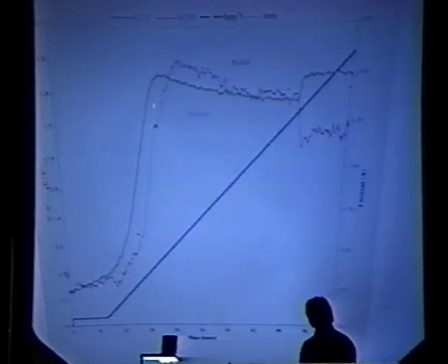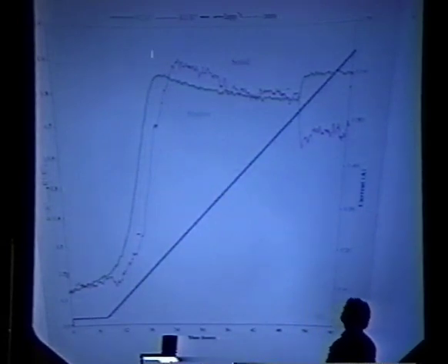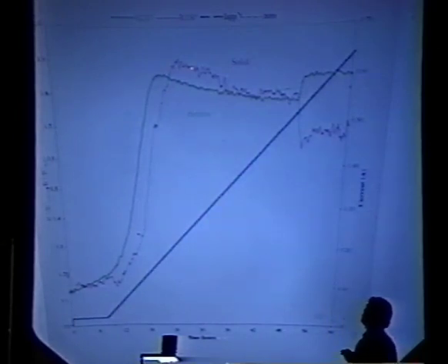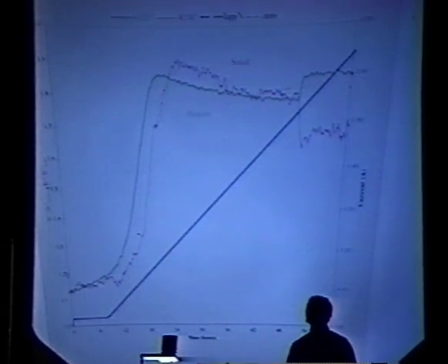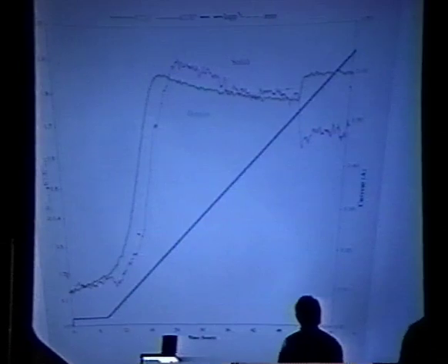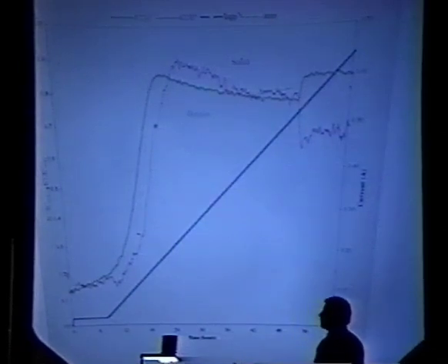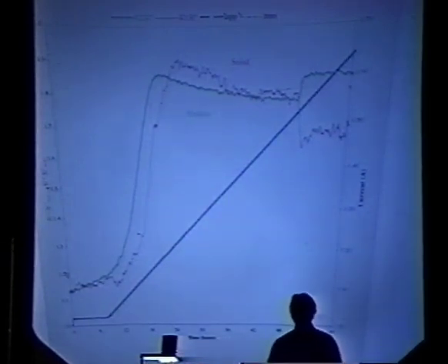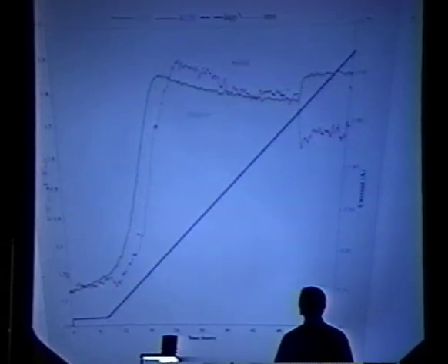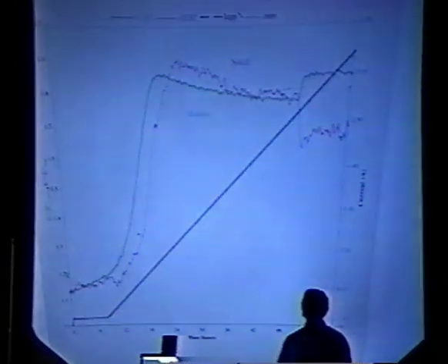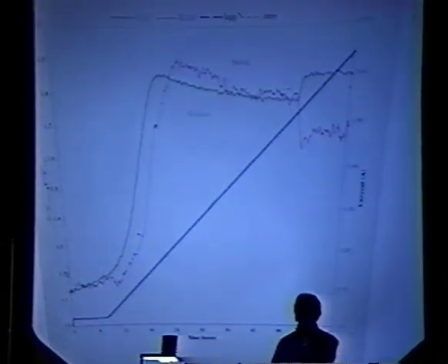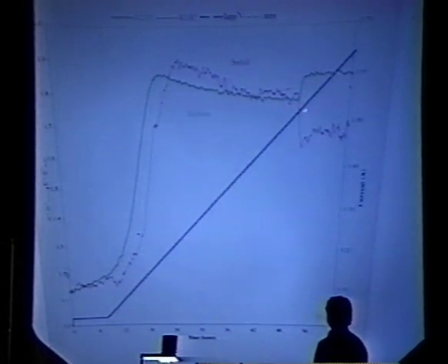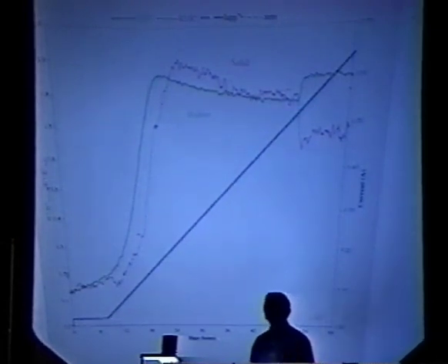But what happens is the resistance ratio increases, desirable, as current ramp increases. This is good. The resistance ratio comes down on the right-hand side of the resistance maximum, as we desire. And at some point, the cathode simply failed. At a resistance ratio of about 1.8, the cathode ruptured. The gas that was pressurized inside the Arata-Zhang double-structured void was released, and the experiment was really dead at that point, although we continued with it for some considerable period of time.